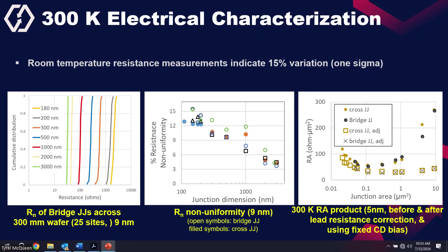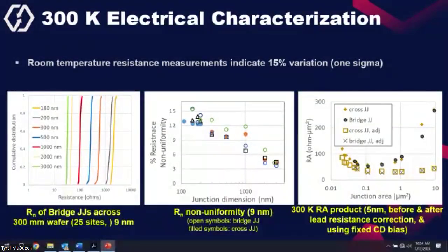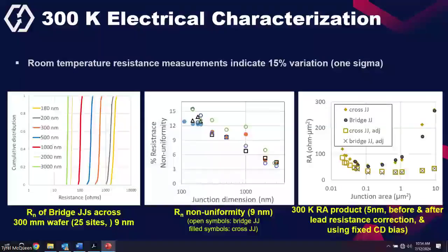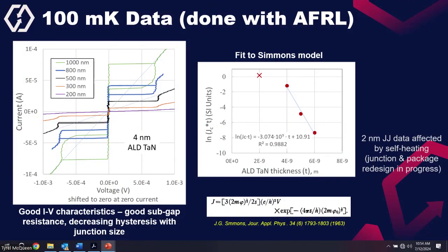And this is the resistance area product, which is an important parameter for a Josephson junction. It shows that this is flat after subtracting the effect of the lead wires, which is again good, and shows that we have good Josephson junction characteristics. So we have established that at room temperature, we have good Josephson junctions. Our next step is to go to low temperature, because for a superconductor, we have to go to temperatures below the superconducting transition temperature in order to determine its characteristics.